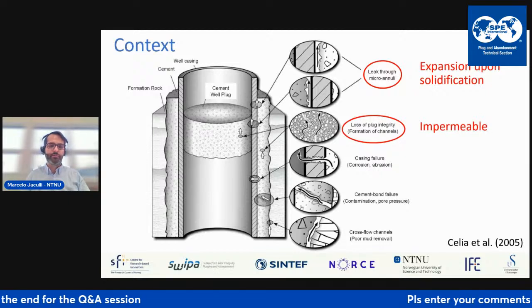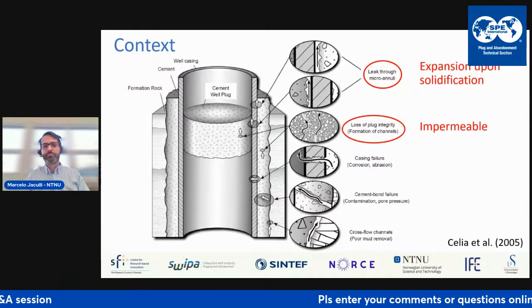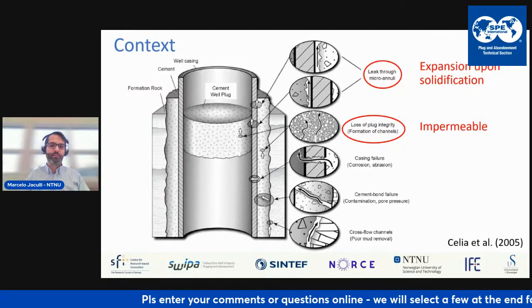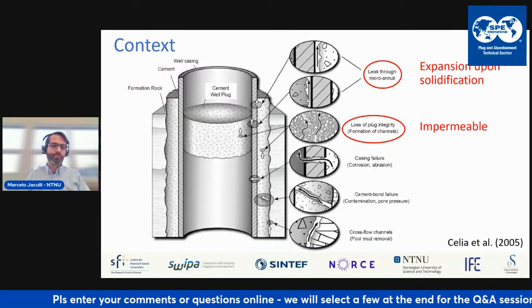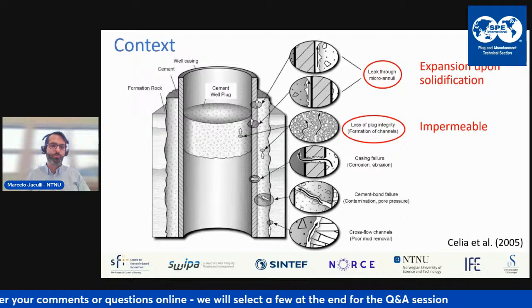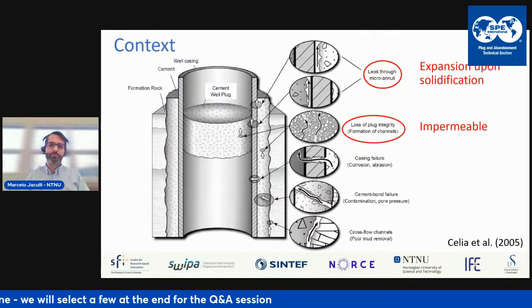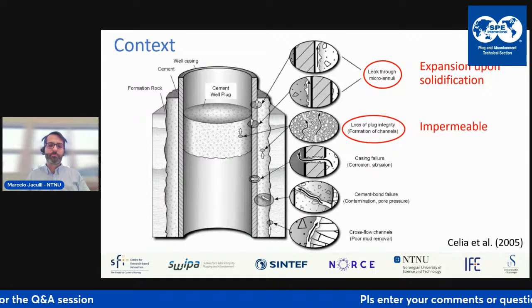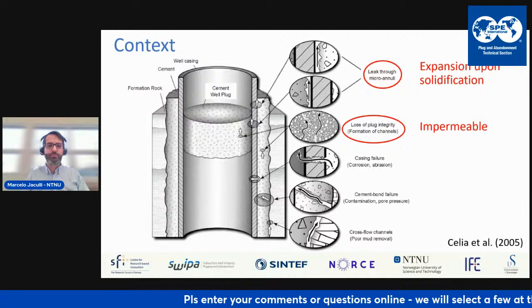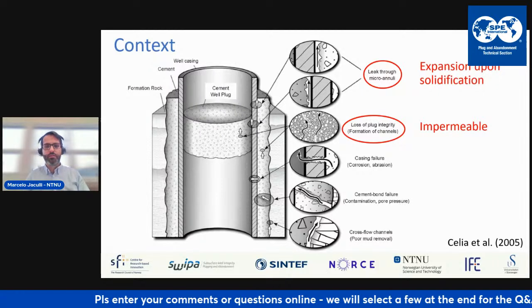Let's say you have some channels through your cement plug. This can be solved by a bismuth plug due to the fact that it's impermeable. Being a metal plug compared to a porous material like cement has this advantage of being impermeable, but it could also provide better sealability in terms of the annuli that can be formed between the plug and the pipe inner wall.